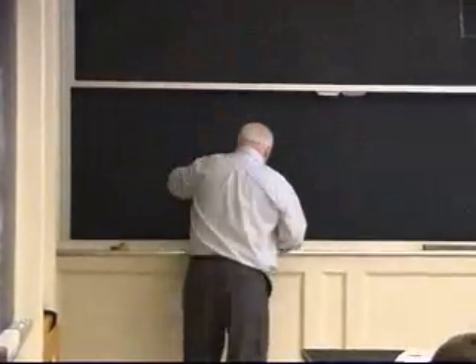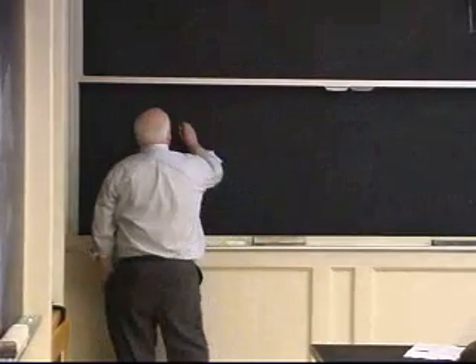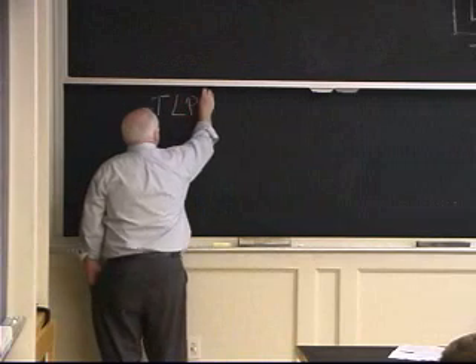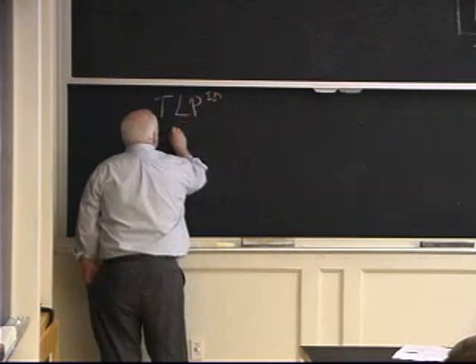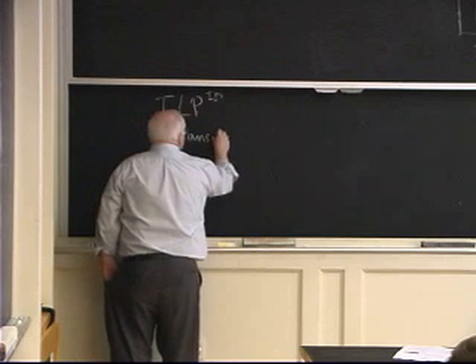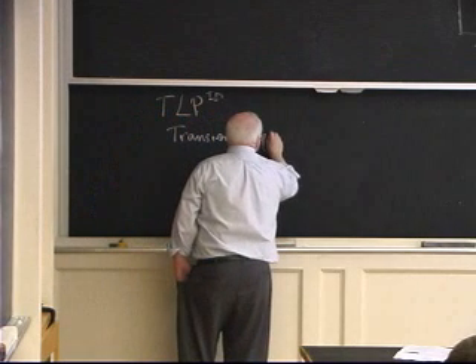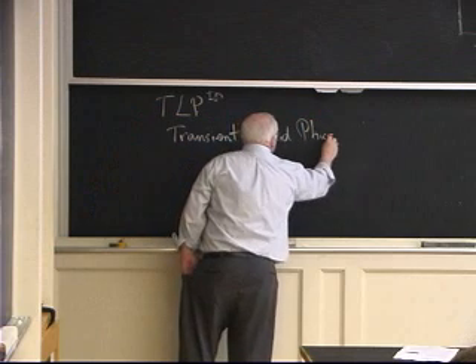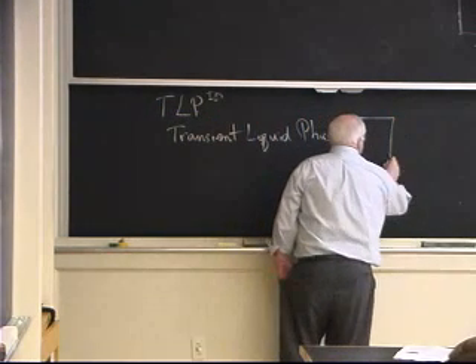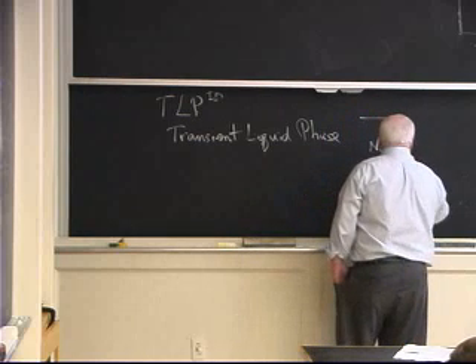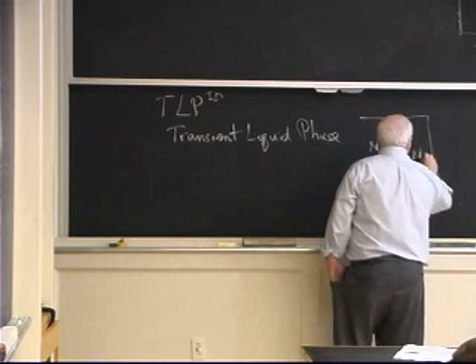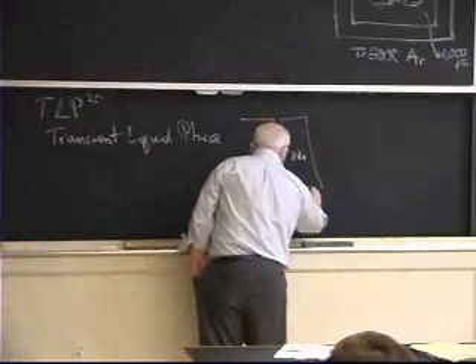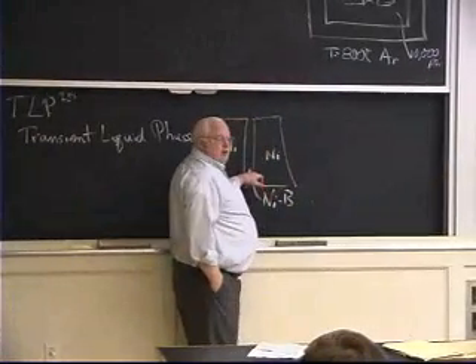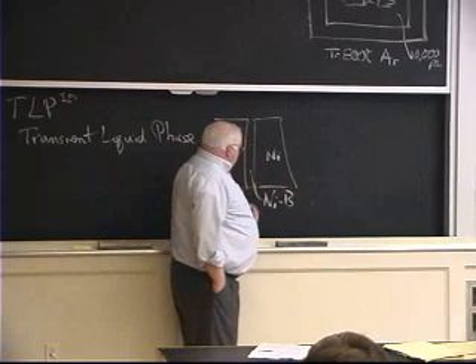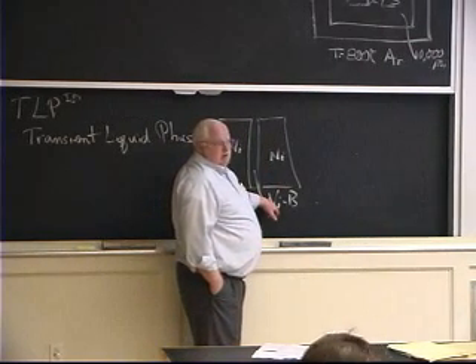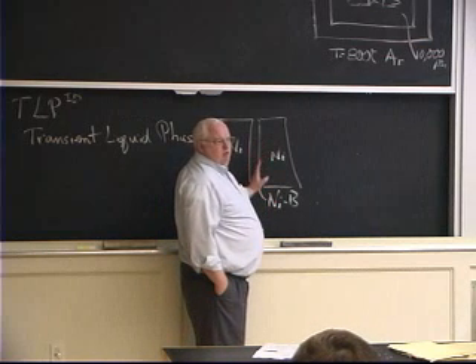In any case, the next thing that people did, and actually it was started in the 1950s, but Pratt & Whitney registered a trademark in 1972 called TLP for transient liquid phase. And TLP bonding, what they did originally, they had nickel-based superalloys. I actually think they discovered this by accident. But anyway, to another nickel-based superalloy. And if you put a nickel-boron alloy in between, boron lowers the melting point of nickel substantially, several hundred degrees centigrade. And actually, we use nickel-boron alloys as brazes. I could make a braze joint between two pieces of nickel with a nickel-boron braze alloy, which melts at a lower temperature.